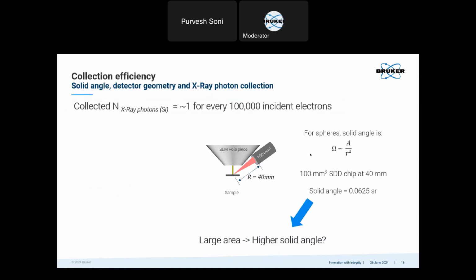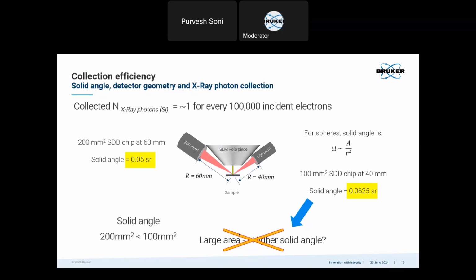So what to do if we want to improve the signal? Can we use a large area detector for higher solid angle? Let's also do this calculation. Instead of 100, let's double the size, 200 square millimeter chip size. Because the detector is quite large, you have to place it further away from the sample. So instead of 40 millimeter for 100 square millimeter, you have maybe now 60 millimeter. Then the solid angle using the same formula will be 0.05 steradian, which is even less than a 100 square millimeter detector. So a large area detector does not naturally mean that you'll have better solid angle.